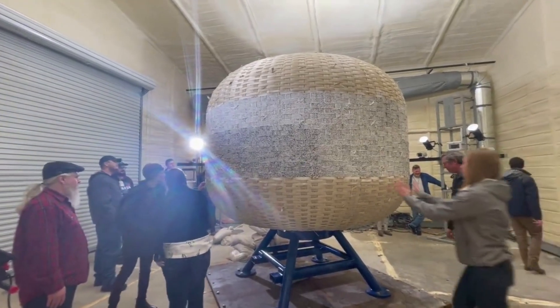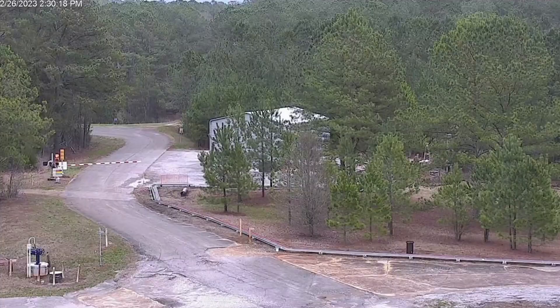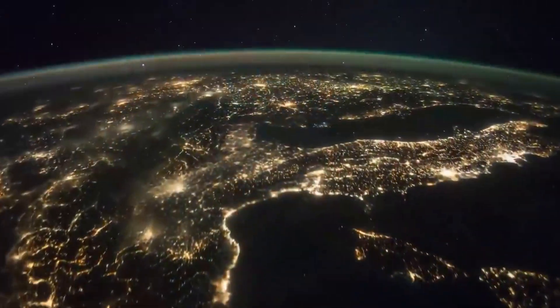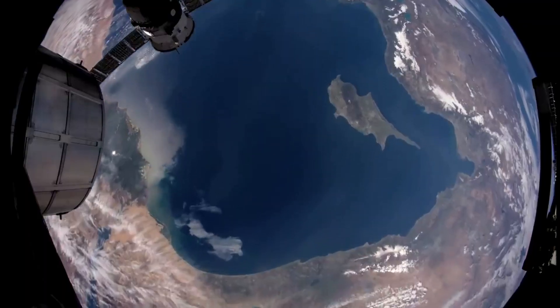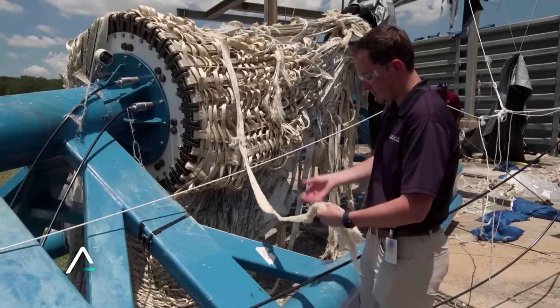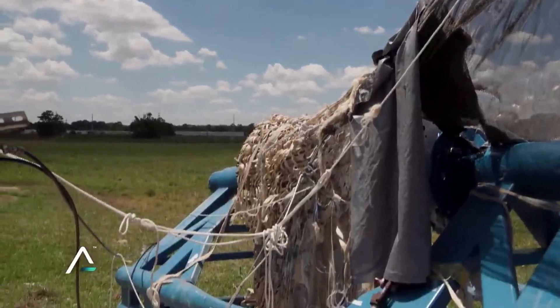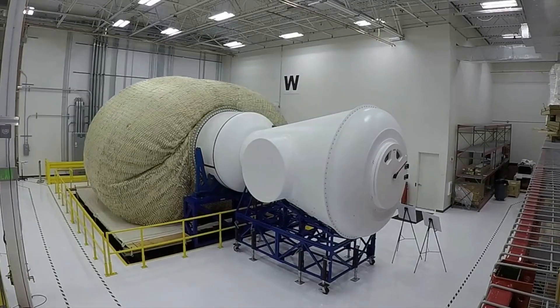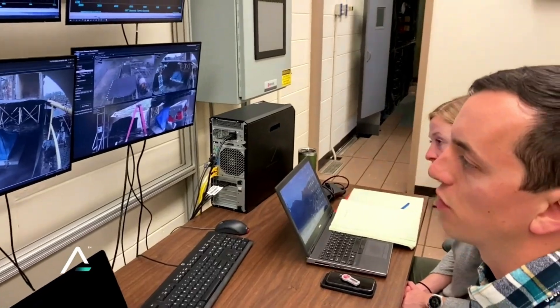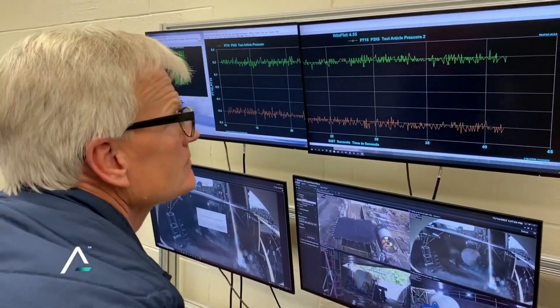Recent testing has provided great results for its future. Just last month, Sierra Space performed a month-long Accelerated Systematic Creep, or ASC, test on LIFE — the first milestone in its 2023 testing campaign. Engineers loaded a one-third scale version of the inflatable habitat with a sustained amount of pressure over an extended period of time until it failed. Per NASA's recommended guidelines for inflatable soft goods certification, the test reached its goal of generating an additional data point — pressure and time to burst — which can be used to estimate the life of the primary pressure shell structure. Sierra Space Chief Engineer for LIFE, Sean Buckley, said: Our testing campaign has demonstrated that our LIFE habitat pressure shell design has a predicted life far greater than 60 years, or 525,600 hours, based on Sierra Space's 15-year on-orbit life requirement and the applied 4x safety factor. We are obviously simulating pressures well in excess of the norm. Test after test, we continue to exceed our program requirements, validating that LIFE's design, manufacturing, and assembly methods are consistent and repeatable. This latest creep test is a different kind of stress test than the two previous ones conducted in July and November, which pressurize units with increasing loads until they burst at maximum or ultimate burst pressure, UBP.